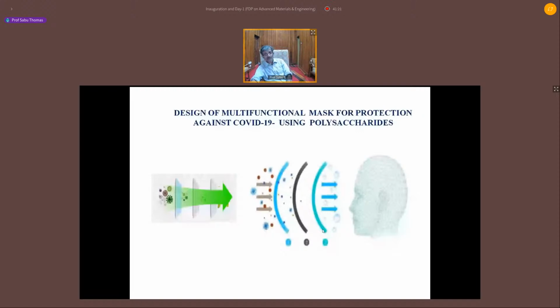So if coronavirus is coming, this coronavirus could be repelled by this outer surface because it is an anti-adhesive, polyelectrolyte coating. And the middle layer is nanocellulose, which is positively charged. If at all some coronavirus is getting in, because sometimes people are very careless in wearing the mask, this coronavirus could be killed by this nanocellulose because it is positively charged. And this has also got an antiviral coating. So this is a design we proposed. You can see our tri-layer mask, the outer layer, the middle layer, inner layer.